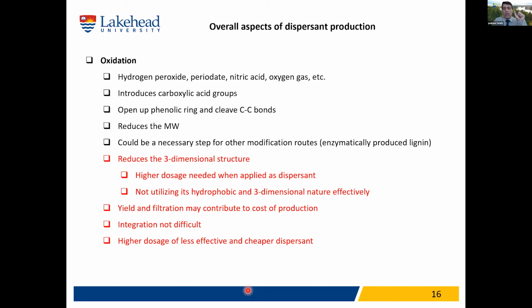That's very important. So when they are smaller and they don't have the 3D structure, maybe you need a higher dosage to have them disperse and to have a good dispersant. This approach is not utilizing the 3D structure of the lignin. On the other hand, when you oxidize the lignin, yield and filtration are important. They may contribute to the cost of production of lignin-based dispersant. But this approach, oxidation, can be utilized in the kraft pulping process. Integration is not difficult.